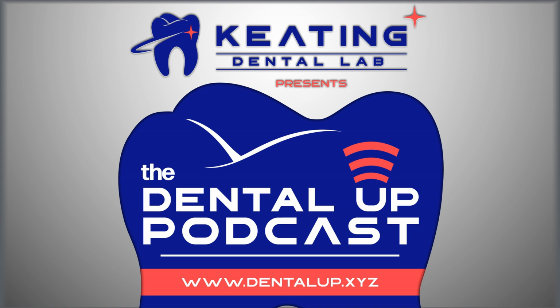And me personally, as a lab technician, I would love to have every single patient's bite force number on the prescription, because if somebody wants straight feldspathic porcelain and their bite force generation is 1,000 newtons, I'm going to say, nope, we can't do that. We need to go to monolithic zirconia. That's our number one problem in the lab: broken glass, broken restorations. And not just this lab, but I'm sure every lab worldwide would really benefit from more patients using your invention and testing their bite force and having that number recorded. It could really steer the dentists and laboratories into making better decisions.